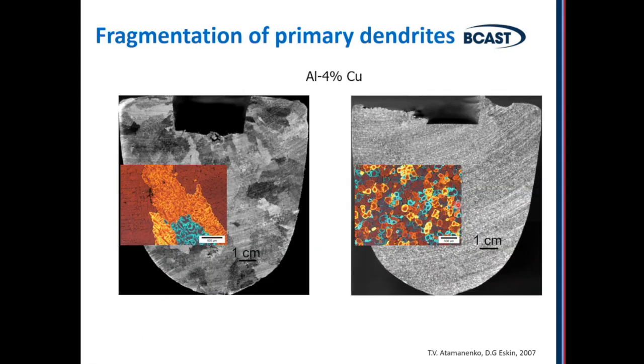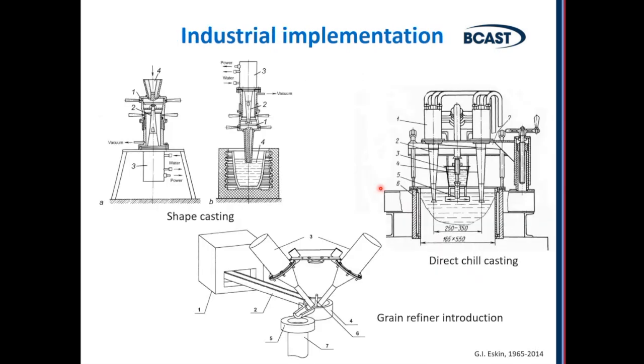Fragmentation of primary dendrites works always. If you do ultrasonic processing during solidification, it always works, but the problem is that you're very limited in volume, because if you go to the semi-solid material, the volume which you can treat is very small, because of course you have a lot of solid material around, so there is a lot of attenuation of the acoustic waves, so you're confined to a very small volume, so practically it can seldom be used.